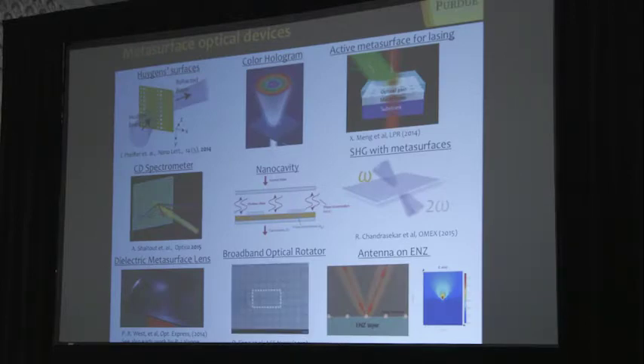Here's just an overview of what we did in our group. I guess it's an excusable bias because that's what we did, although, again, there are many other spectacular works done by other groups as well. You could make a Huygens surface. What this Huygens surface is about is that you control not only the coupling to the electrical field component, but also to the magnetic one. And for that, you add to these dipole antennas also magnetic dipole antennas. If you do so, you could match the impedance because you control mu as well. And if you match impedance, you actually could get rid of reflection.